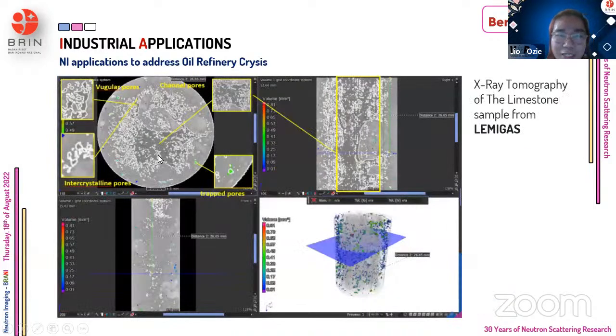Okay, so you can see this pore channel. Actually, for the case of the limestone, it's completely X-ray. It's much better to see the pores of the limestone sample. But for the sandstone sample, you can deal with it with neutron also.